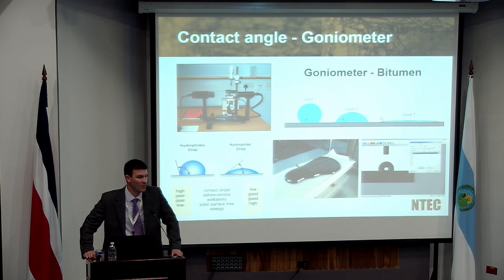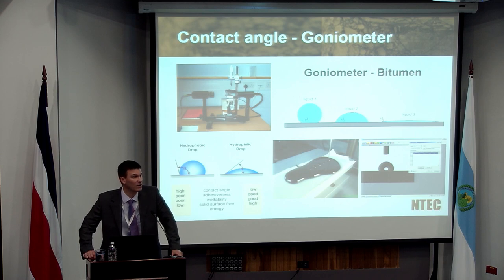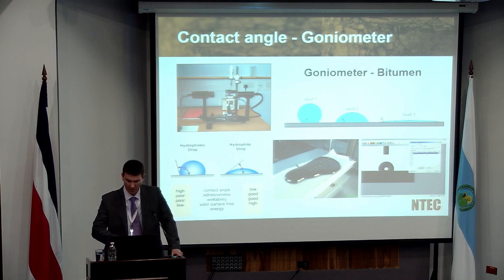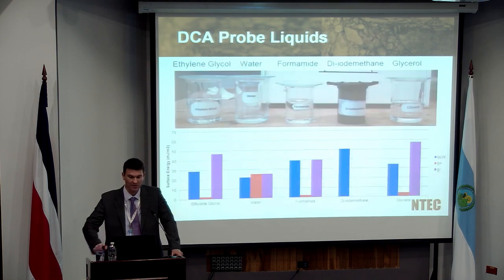That tends to occur if you have a very polar liquid. Bitumen tends to be mainly non-polar in nature. If you put a very polar material, such as water, for example, it will definitely form a very high contact angle. And then we get all the way to the other extreme. If we took a very non-polar material and put it onto the bitumen, it will actually want to coat the bitumen, and therefore the contact angles will be a lot lower. So using a whole range of different probe liquids, we can get a range of different behaviors. We've used five in this particular case.